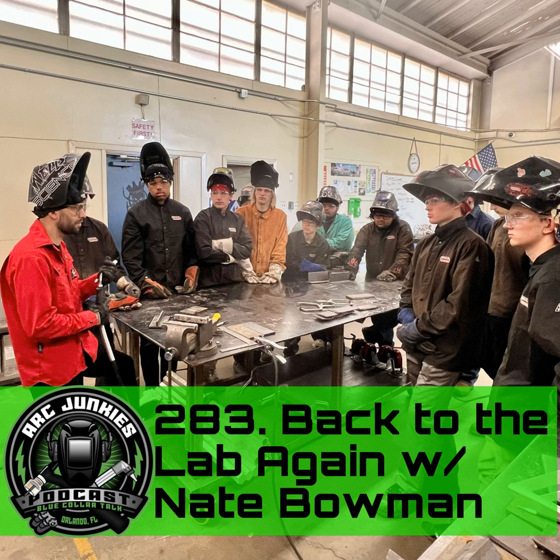He's doing vertical. He wanted to switch away from flux core because he heard you can run pulse vertical, out of position. And he was just having a hard time with the testing, trying to run pulse vertical. He's like, I can't get this thing to lay in there really well. Well, in order to run pulse vertical, you can only run it at maybe 350 inches a minute, which is basically the upper end of short circuit anyways. With .035, right around 350 inches a minute is just shy of 200 amps. Well, in pulse, you're pulsing your amperage and you get a lot of that puddle stability, but your deposition rate is extremely low.